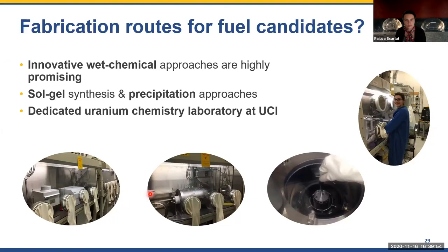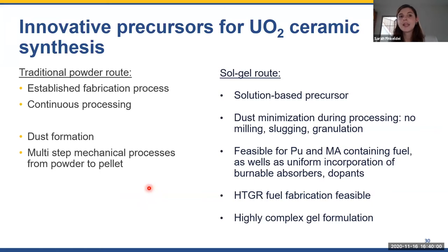And in my laboratories at UCI, we have a strong emphasis on the sol-gel technique. So if we are thinking about the fabrication of precursors for UO2 ceramics, traditional routes utilize powders, which have certain benefits and disadvantages. If we use the sol-gel route, we are using a solution-based precursor, so no powders, and that minimizes dust formation. It's also feasible for fuel that contains plutonium and minor actinides, as well as high temperature gas cooled reactor fuel fabrication. And the only drawback is a pretty complex gel formulation.